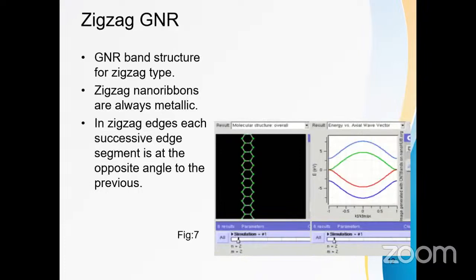Zigzag GNR type: this is the band structure of the zigzag type. Zigzag nanoribbons are always metallic. In zigzag edges, each successive edge segment is at the opposite angle to the previous one. Calculations based on tight binding theory predict that zigzag GNRs are always metallic.